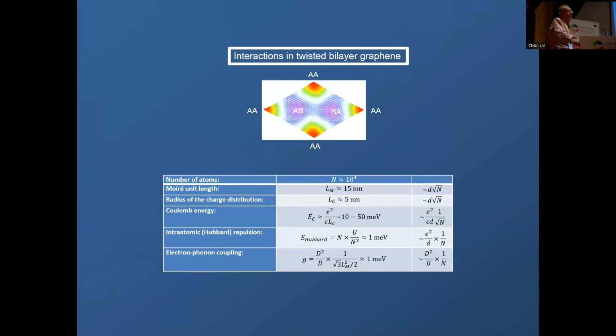Okay, so what I have tried to explain to you is that there are flat bands, definitely, and that implies that interactions are important. So here there is a description of different interactions. The nice thing of having these very large unit cells, in this case, these unit cells contain about 10,000 atoms, is that you can use precisely that number, 10,000, as a large number, which allows you to classify the interactions depending on how the energy scales associated to those interactions scale with this number n. And it turns out that the leading interaction is the long-range Coulomb interaction.